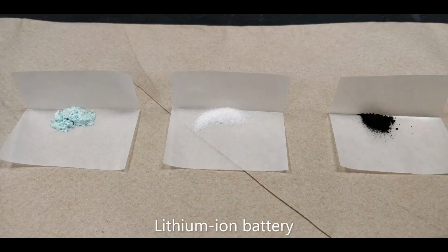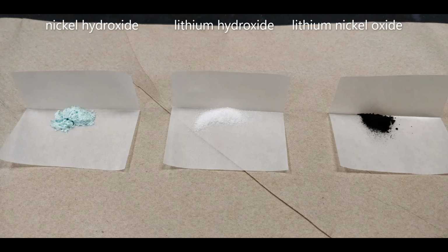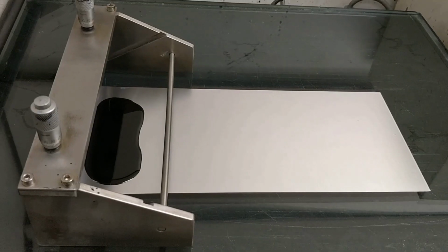As a second demonstration, we are going to have an inside look into a typical lithium-ion battery. The first step of making a battery is the synthesis of cathode. In a typical synthesis, nickel hydroxide is mixed with lithium hydroxide and fired at high temperatures in an oxygen furnace to get the dark powder lithium nickel oxide. During the reaction, nickel is oxidized from a 2-valent state to the 3-valent state, and due to the increased nickel-oxygen covalency, the powder gets dark.